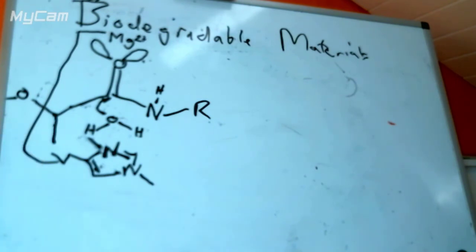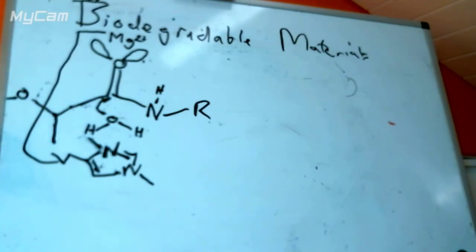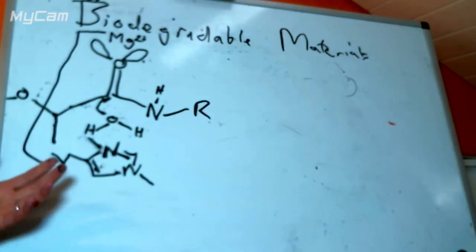So if we take a polylactic acid molecule, we can take one form with this arm in one direction, and it will degrade very quickly in a body, and we put it in the other direction, and it takes a very long time indeed because the enzyme can't grab it. So that is specific, but not necessarily helpful. It's useful to us because we can use it for things.